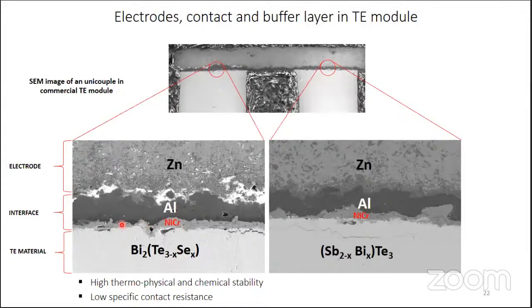Here the nickel chromium is the main content. This is the one which prevents the diffusion, and it is keeping things stable. At the same time, it gives good electrical conductivity with very low contact resistance. So this is for N-type material. This is how it is integrated in the commercial module. Cold side, it's no problem because the cold side is at low temperature, so lead soldering is good enough to do it.